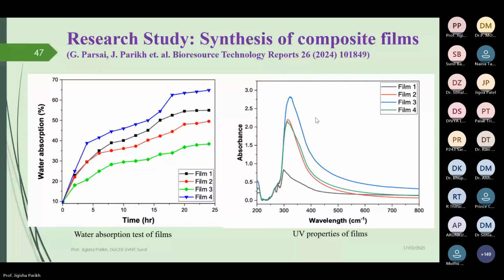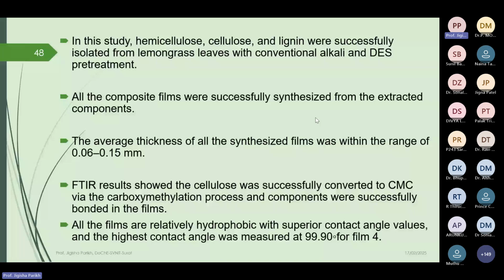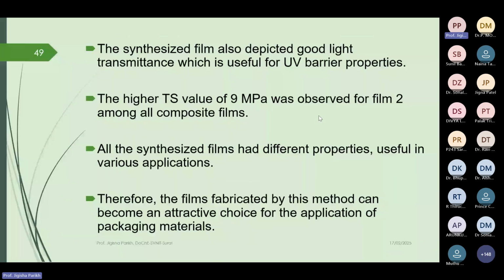So overall, in this study, hemicellulose, cellulose, and lignin were successfully isolated from lemongrass leaves with conventional alkali and DES pretreatment. All the composite films were successfully synthesized and the methodology was optimized also. The average thickness was in the range of 0.06 to 0.15 mm. FTIR results showed the cellulose was successfully converted to CMC via the carboxymethylation process, and the components were successfully bonded in the films. All the films are relatively hydrophobic with superior contact angle, particularly film 4 with a 99.9 degree contact angle. The synthesized films depicted good light transmittance, which is useful for UV barrier properties. A tensile strength value of 9 MPa was observed with film 2 among all composite films.